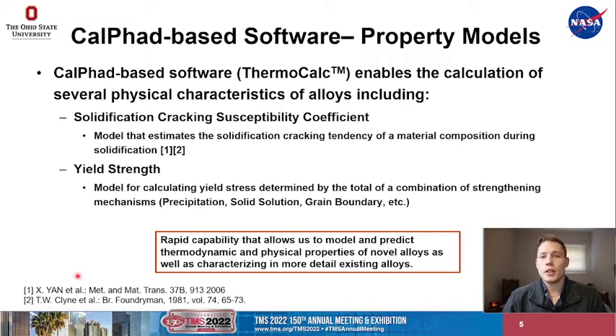property, which includes a model for calculating yield stress determined by the total of a combination of strengthening mechanisms, including precipitation, solid solution, grain boundary, etc. The yield strength can provide information about solid state cracking. We were hoping that it would help us to estimate the ductile-brittle transition temperature.